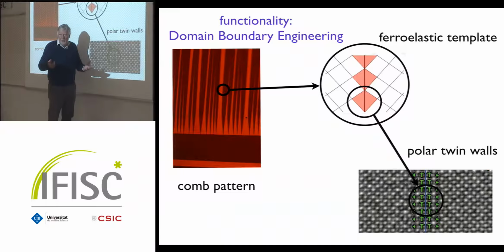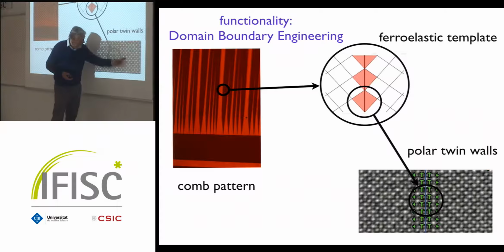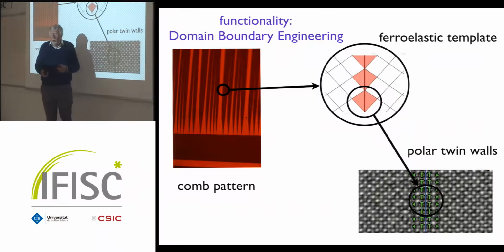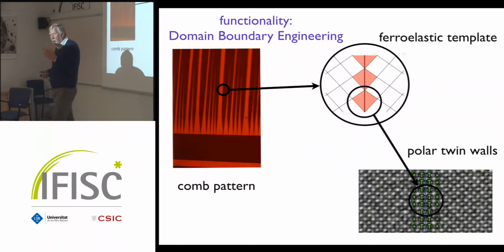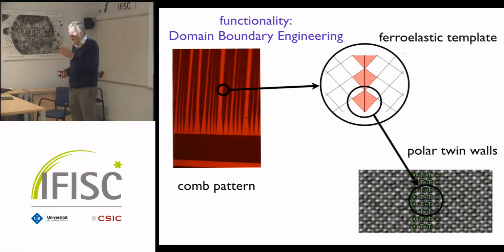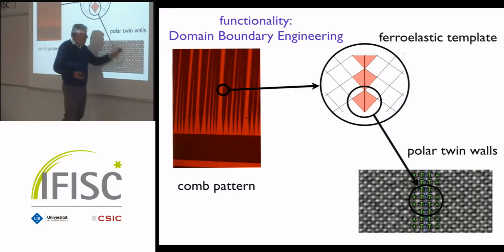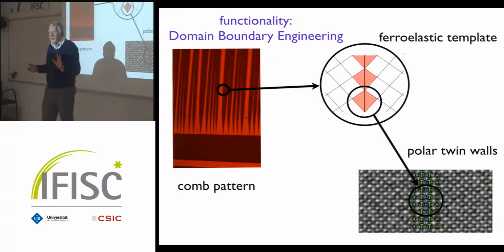I mean, we were talking about it until we were blue in our face. But of course, we couldn't prove it. We could do DFT calculations. We could show the energy minimum is not in the middle. But if you can't show it, nobody believes you. Now we know that all these atoms here, these are titanium atoms, are not in the middle. They're in the middle here and here, but not in the wall. So the wall has therefore dipole moments, polarity. If it has polarity, you can put a field on and you can play with it. So you can reverse them, you can tilt them over to that side, tilt them over to that side, just by an external field. Very small field.